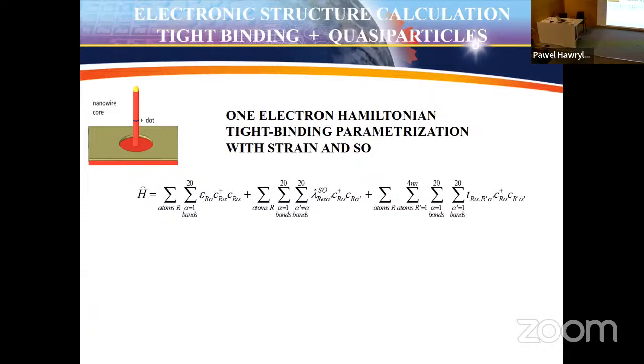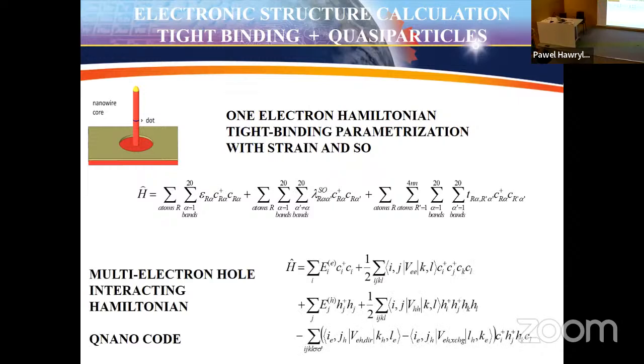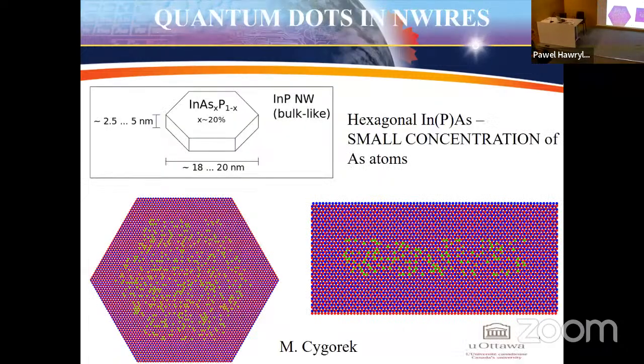So we have a single particle Hamiltonian. It's a tight binding Hamiltonian fitted to the ab initio results. And then we have the multi-electron hole interaction Hamiltonian. All of this is handled in our QNANO code. The properties of these materials are such that we have a relatively small arsenic concentration. Here you see arsenic atoms from the top. The wire has a hexagonal cross section, and this is from the side. So you see this is far from perfect, and each dot has a slightly different placement of arsenic atoms versus phosphorus atoms.